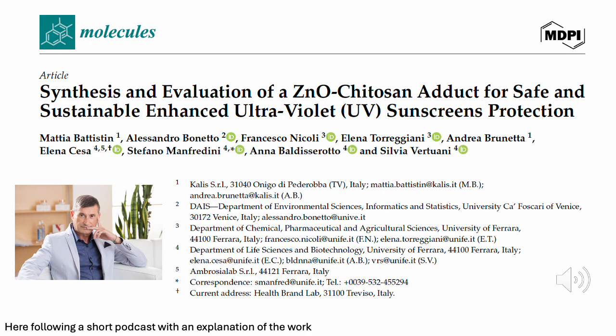They used a test with a blue dye called acid blue 9. So basically, when this dye is exposed to UV light in the presence of something that's photocatalytically active, like plain zinc oxide, it gets broken down, and the blue color fades. So they had a solution of the dye with either plain zinc oxide or ZnO@CS and exposed them to UV light for a certain amount of time. And then they measured how much of the dye was degraded.